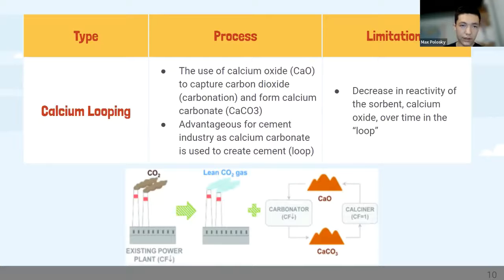We also have the commonly used calcium looping, which is using calcium oxide to capture CO2 and react with it to create calcium carbonate, which is of course good because calcium carbonate is a key ingredient in making cement. And this creates a sort of loop that theoretically can go on forever, but the issue is that as you go through the loop multiple times, the calcium oxide degrades in reactivity, and so unfortunately it is not infinite.